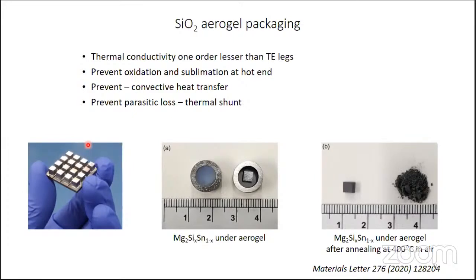There is a material called aerogel, silica aerogel. This material is known for extremely low thermal conductivity. In fact, the thermal conductivity of this material is one order lower than most thermoelectric materials. So what we have done is use it in our module, filling all the gaps between the P and N legs. The empty spaces in the device, we are filling with this silica aerogel, so that there will not be any heat transfer from hot side to cold side through the aerogel. At the same time, there will not be any sublimation. The aerogel will prevent sublimation and oxidation, so that the leg will be protected.